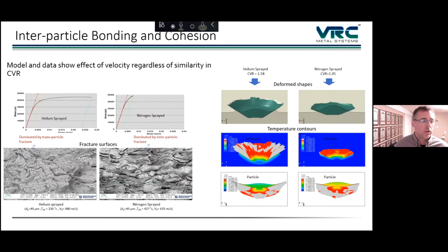All right, so once you figure out the substrate interface, now we have to also think about the interparticle bonding, because that's where you get your strength from. So this shows two examples. One was a lower temperature, high velocity spray, which is to the left. And the image to the right is the nitrogen sprayed, which is going to be higher temperature, lower velocity.